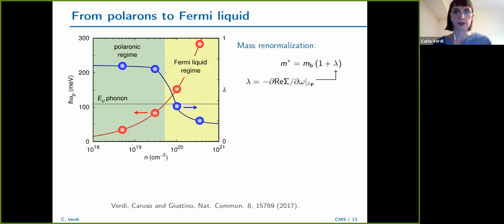To be more quantitative, one can actually estimate the mass renormalization. Our electronic polaron, well, the electron, has a certain effective mass, which we call here the bare effective mass, from what you get from, let's say, a DFT calculation. Due to the electron-phonon coupling, it will have a larger mass, called here m star. The mass renormalization parameter is estimated from the self-energy again. This is plotted in blue here, the lambda parameter. You see that the renormalization is roughly constant at low and intermediate doping level, and then it drops. It becomes much lower.